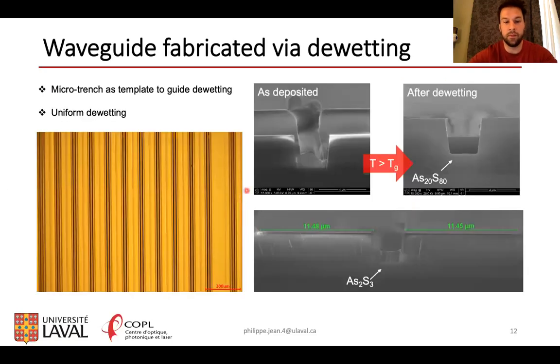So if we look at some examples of optical waveguides fabricated from dewetting, if we check the before and after picture, we can see here maybe a worst-case scenario of thin film deposition, where because the microtrench is pretty narrow, the deposition is not uniform inside the trench. And you see you have this bump, and you also have this remaining top layer, which will retract. If we look at the picture after dewetting, the rim is actually retracted outside of the picture, and the waveguide core is a very nice strip waveguide with a flat top.